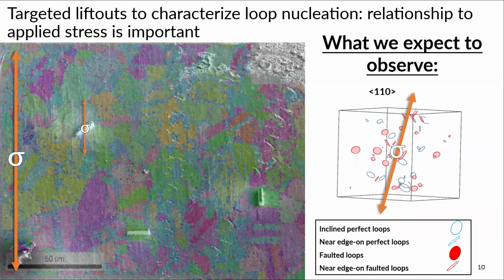So on the right-hand side, we expect to observe multiple different types of loops. So perfect loops, which are atoms that basically conglomerate, they come together and literally form loops. And those are not going to have any contrast in the middle of them. But then we have faulted loops, which are like stacking faults. So you've got these loops that come together, and then there's a bunch of interstitials within that loop. So it's usually dark or light, whichever way you look at it in the TEM.